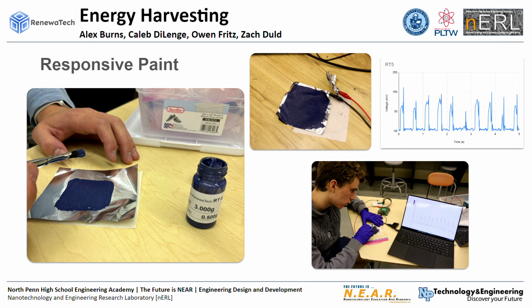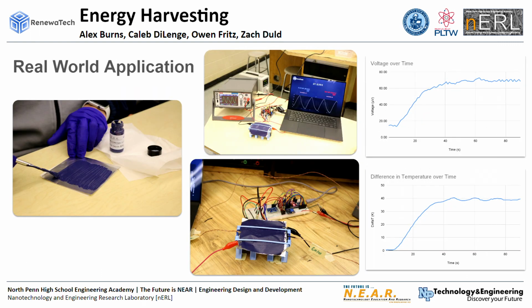We then made another paint sample mixing PVDF and bismuth telluride. After painting it again, our results were very successful due to the fact that we were able to measure both thermo and piezo at the exact same time. This could be applied as a clear coat to things like windows, or as a paint to homes, cars, and buildings, increasing the efficiency or generating electricity for those things.